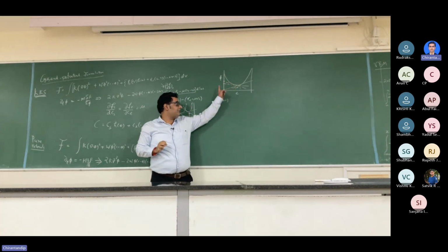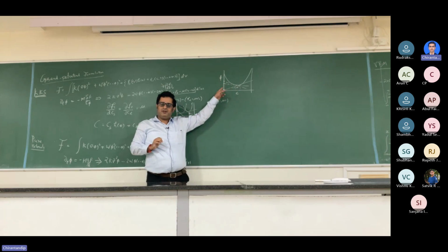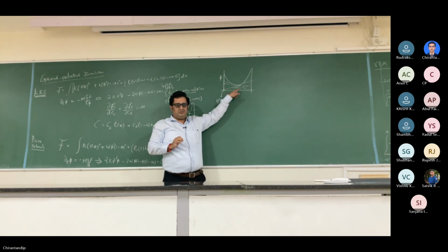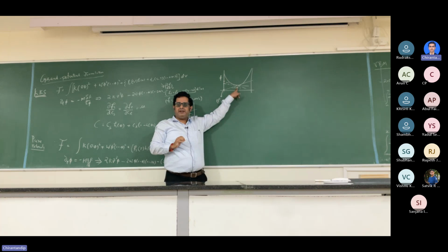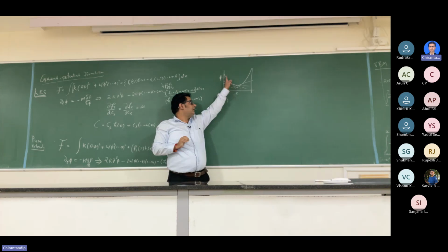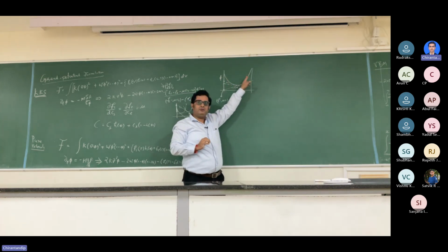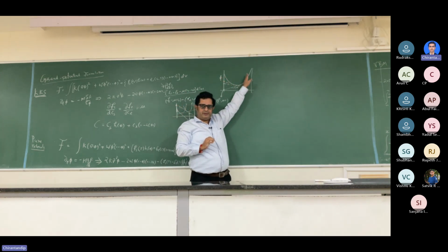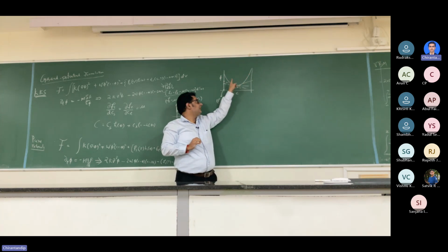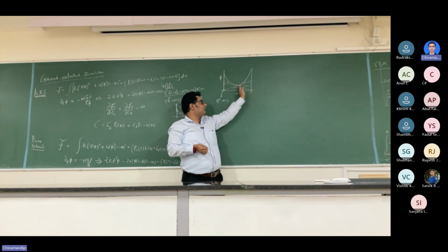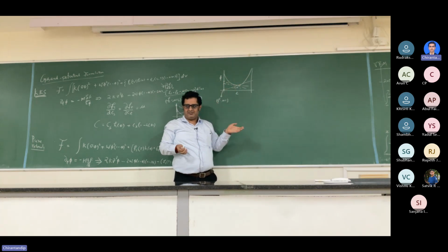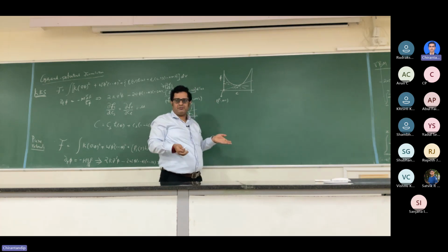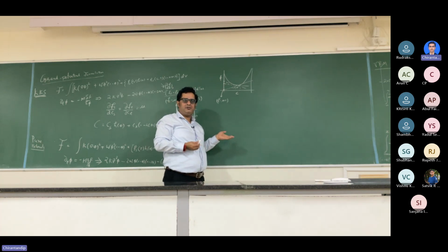Remember, for each composition for this type of curve, you have a unique slope, right? The slope will not be repeated. That means for a given composition, you have a unique mu, and as you change composition, you have a unique set of slopes, and for each of those slopes you have the intercept, right? And since these are tangents, what you will get out of the envelope of those tangents will be the curve itself, right? So essentially, you are not losing information, but representing the information separately.